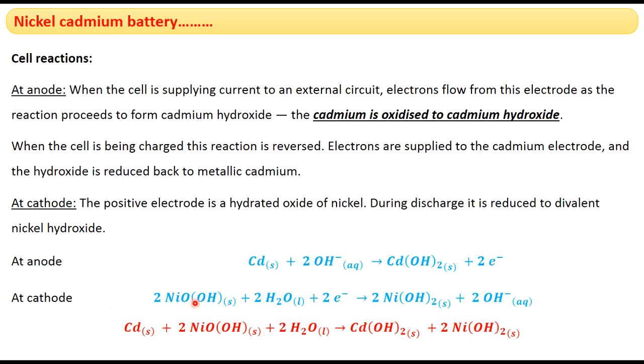Now the nickel oxyhydroxide, which is the active material, undergoes reduction by consuming 2 electrons which have come all the way from the anode, and also consumes 2 water molecules, forming nickel hydroxide and 2 hydroxyl ions, 2 OH minus ions. This is the reaction occurring at the cathode, and the overall reaction will be cadmium solid plus 2 nickel oxyhydroxide plus 2 H2O gives rise to cadmium hydroxide plus 2 nickel hydroxide molecules. This is the overall reaction. These are the reactions occurring during discharging while using the battery. Once the battery is out of charge, it should be charged. During charging, the reactions occurring are the reverse to these reactions.